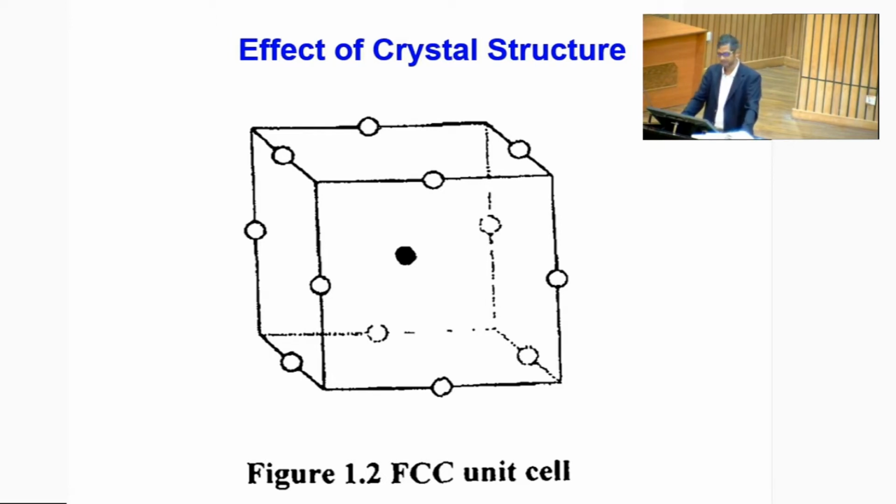That's obvious because if you consider an FCC structure, you know that this is the structure of FCC which is shown on your screen. As you see here, there is a central atom. If I put it around which, there are 12 FCC atoms. So that's a 13 atom cluster, A13, in which one atom is a bulk atom, with all bonds satisfied, but the other 12 atoms are surface atoms, right? So that's our first cluster, first layer consisting of 12 atoms, if we consider the FCC lattice, correct?